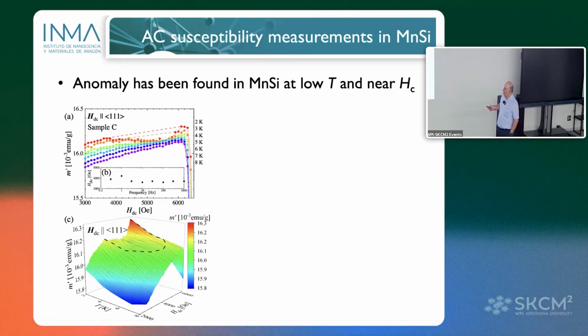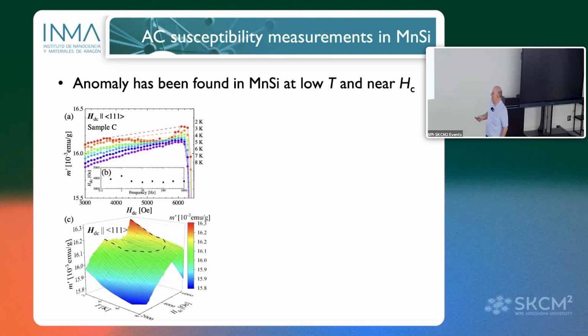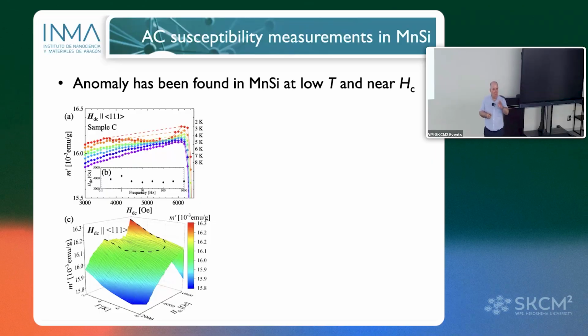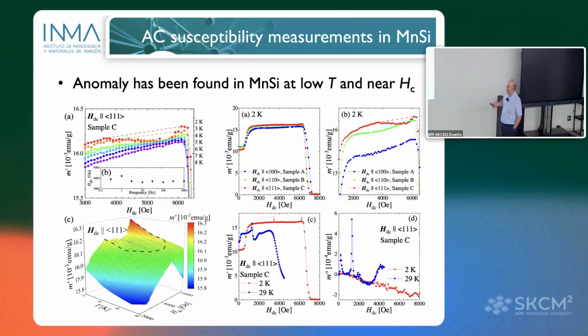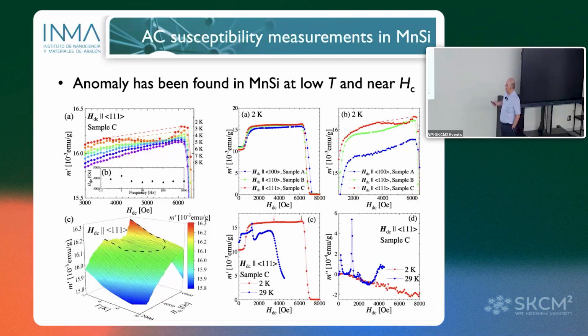We observed that at low temperature and high magnetic field, high with respect to the ferromagnetic state, from 5,000 Gauss to 6,000, there is an anomaly in the AC magnetization. This anomaly was independent of the frequency. You can see that it's very difficult to observe, but our colleague Masaki Mito sensei was able to find a small variation in the AC magnetization. However, considering other orientations, we don't see the anomaly. This was reproducible: considering another sample, or changing the orientation on the same sample, you were not able to see it.